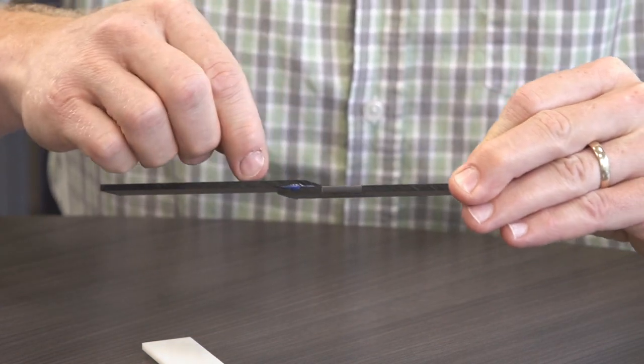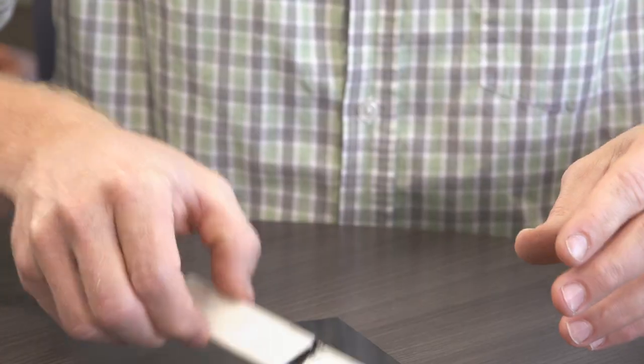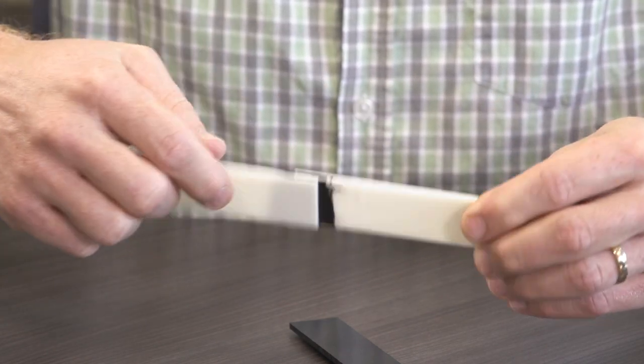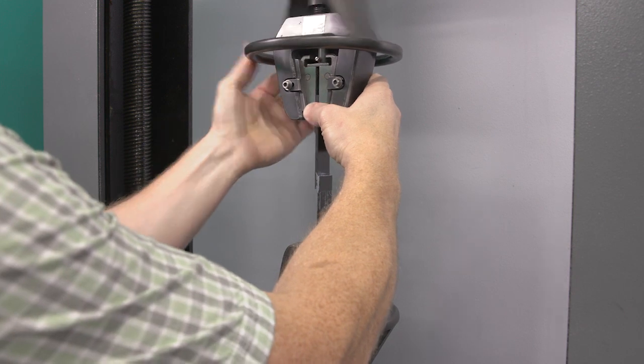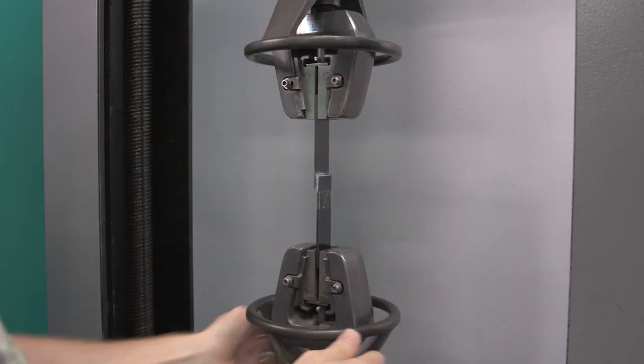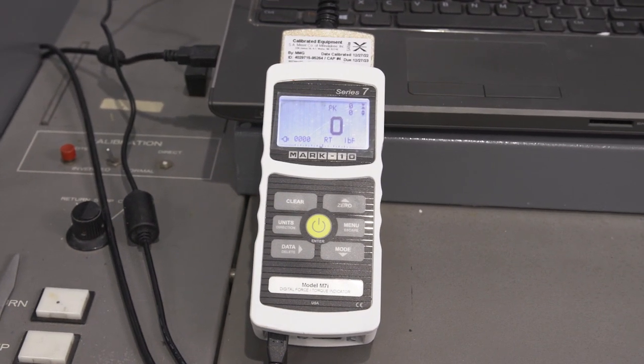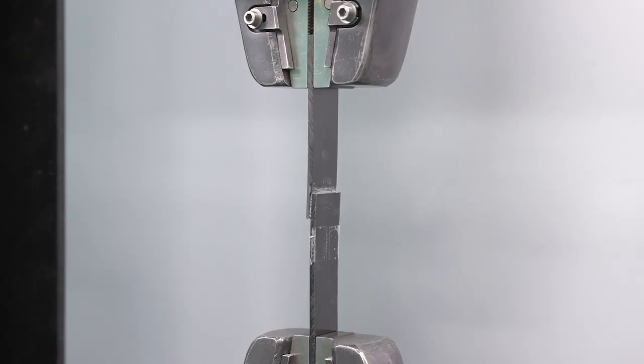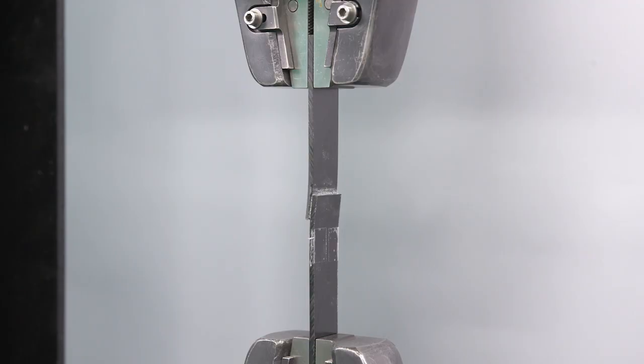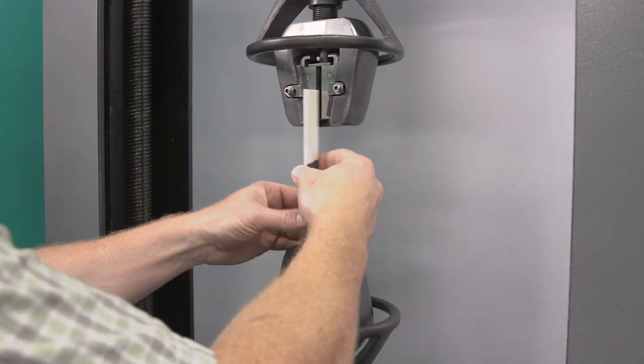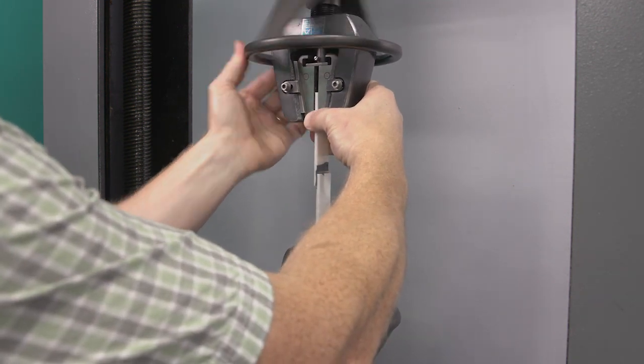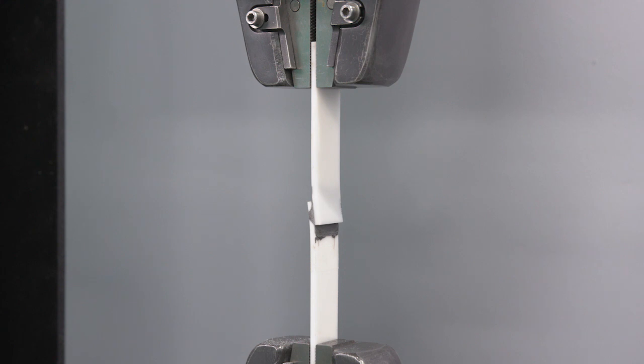When testing the adhesion of a potting compound, an excellent test method is a modified version of ASTM D1002 lap shear adhesion test. This is a robust test method that is effective at determining the relative adhesion to multiple substrates. Though this test method calls out for metal bonding, any substrate like ABS, nylon, polycarbonate, etc. can be tested. The test is conducted by bonding two flat pieces of substrate by a 1 inch by ½ inch overlap. This coupon is then pulled at 0.05 inches per minute on a universal testing instrument. The maximum force attained at the failure of the bond line is divided by 0.5 square inches of the overlap area to determine the lap shear adhesion in PSI.